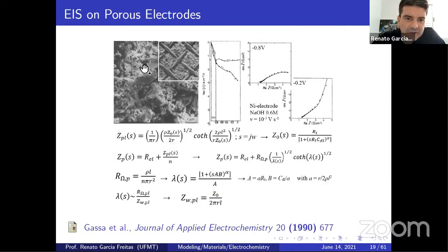And Gassa studied nickel, like here. In the first moment, we have nickel in 0.6 molar hydroxide, isn't it? So we have a Tafel plot like there. We go to 0 up to there, and I have a Tafel plot, observe it here, and they obtained the impedance. Like here, the corrosion of the nickel mesh, and the corrosion soon after applying an anodic voltage gives a very porous morphology like this one. Previously, after. So we have this one, and at minus 0.8 we have this profile, and at 0.2 voltage, which is located down there, anodic current, we have this one, isn't it?